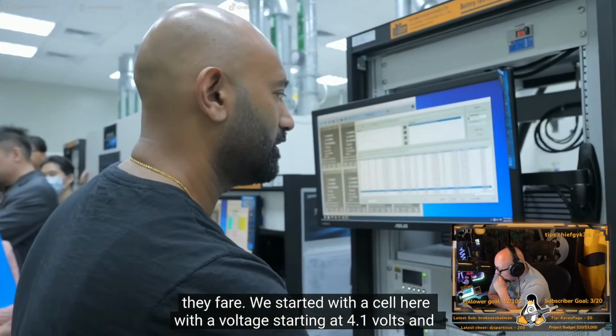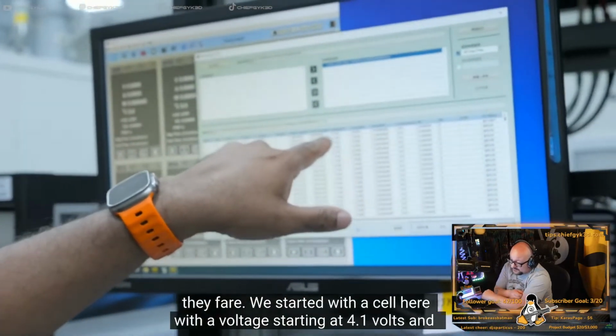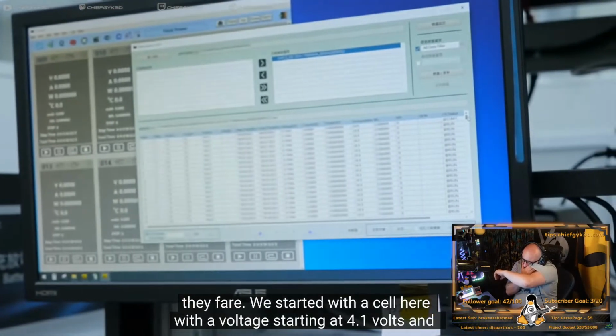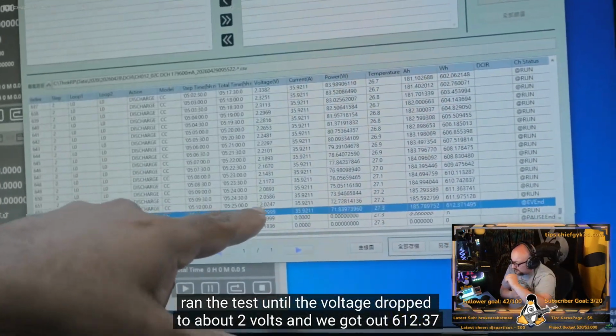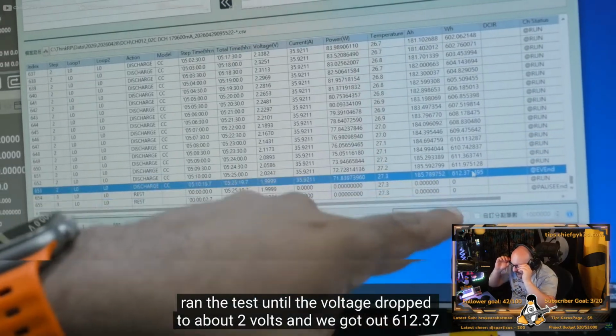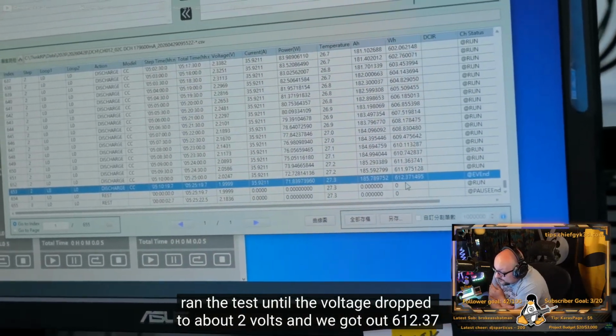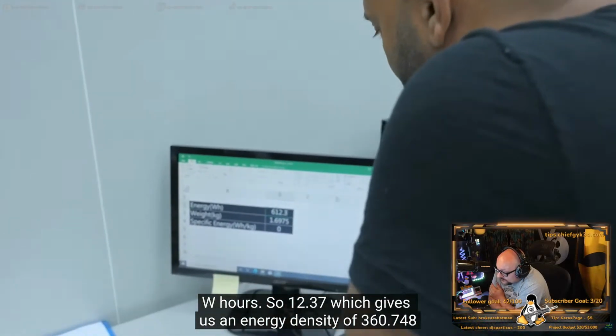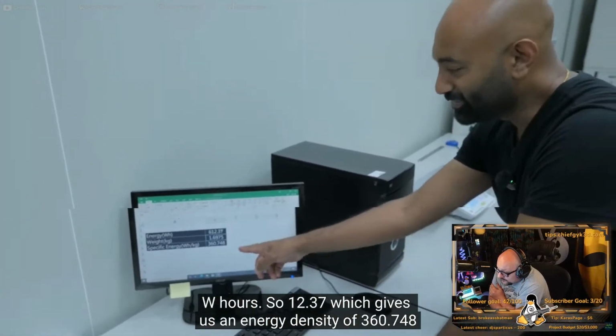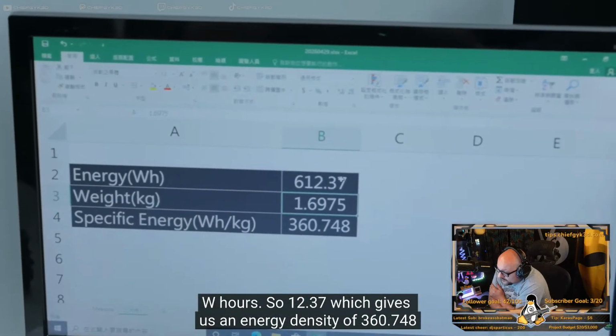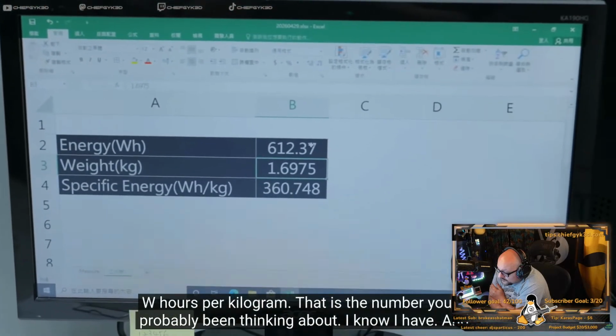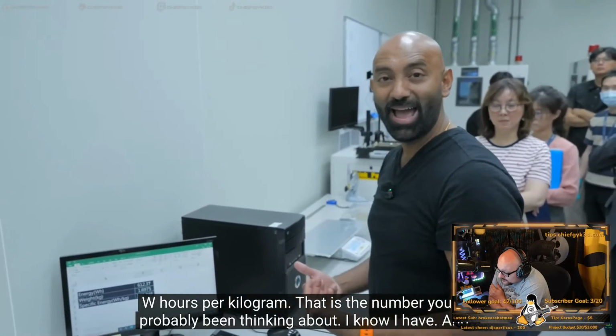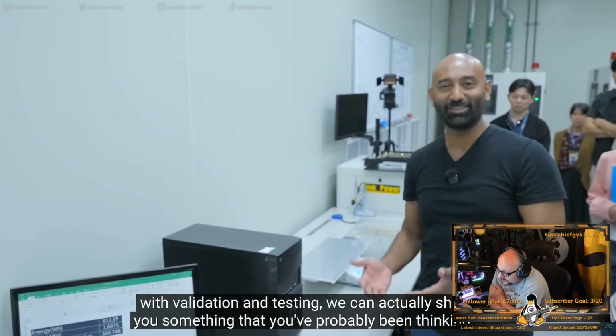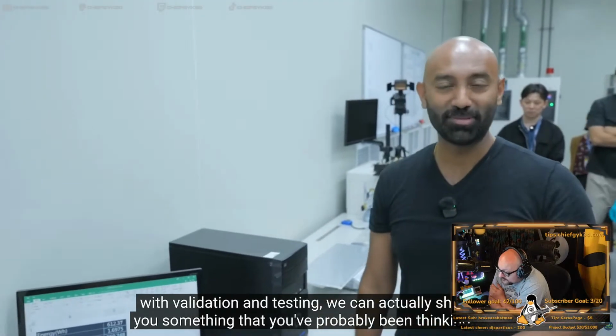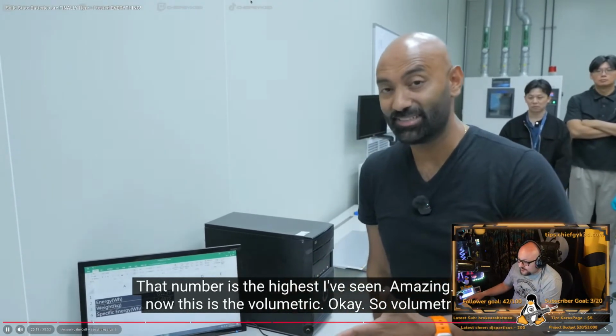We started with a cell here with a voltage starting at 4.1 volts and ran the test until the voltage dropped to about 2 volts. Oh, wow, it gets very low. 612.37 watt hours. Wow. Which gives us an energy density of 360.748 watt hours per kilogram. That is a number you've probably been thinking about. I know I have. And with validation and testing, we can actually show you. That number is the highest I've seen.